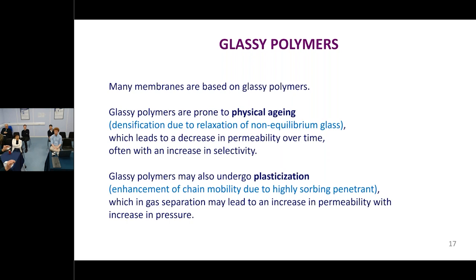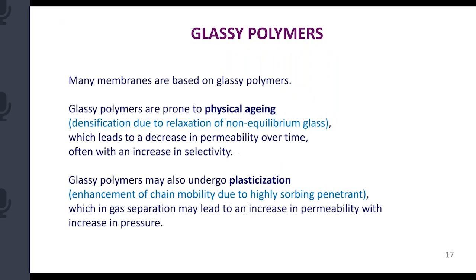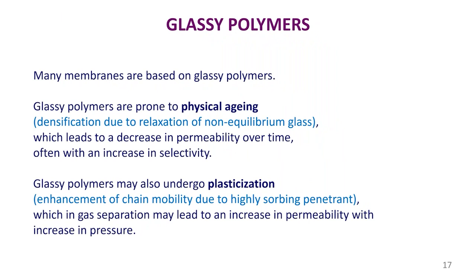If, for example, we're doing a gas separation, and one of the things we're looking at is how we can remove carbon dioxide, either from flue gases or from biogases or something like that. And carbon dioxide interacts very strongly with many polymers, including the ones that we look at. It's also almost like a little solvent for the polymers, where it changes the polymer. It creates more free volume, it creates more mobility just by having it there. And that in turn affects the permeation behavior.